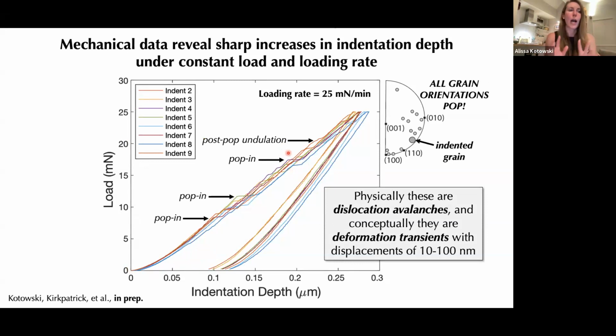But conceptually, I want you to think of these as transients. These have sudden displacements on the order of tens to hundreds of nanometers. They arise spontaneously in the rock from loading a crystal at a constant rate, and they occur for basically all grain orientations that we measured.